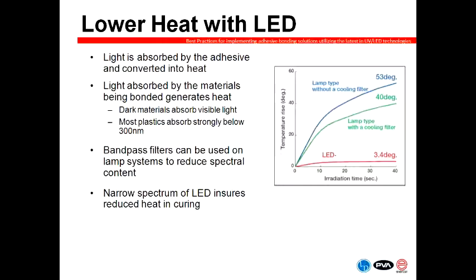So if you're introducing a broad spectrum of light, such as a lamp-based system, only a portion of that spectrum may be used by the adhesive, whereas a large portion of that may be absorbed by the parts, generating heat. Now, with the lamp systems, we do use bandpass filters. So we filter out some of the unwanted wavelengths of light in order to reduce the heat. But certainly the narrow spectrum of the LEDs ensures the lowest amount of heat. So for many different applications where the heat is critical, and I mentioned before some of the applications like the OLED displays or touch panels, where it's really critical for their yields that they minimize the amount of heat, that's why some of these applications are now looking to transition to LED, because they have the benefit of that narrow spectrum reduced heat during the curing process. On to the next slide, please.